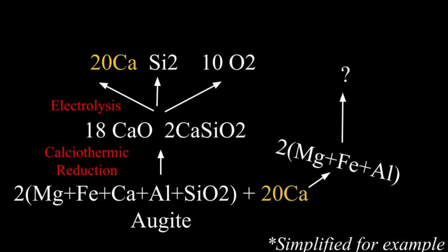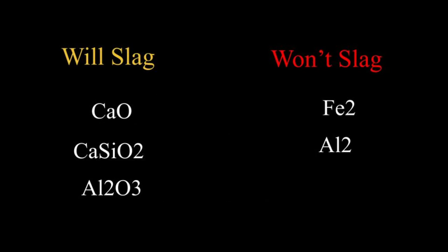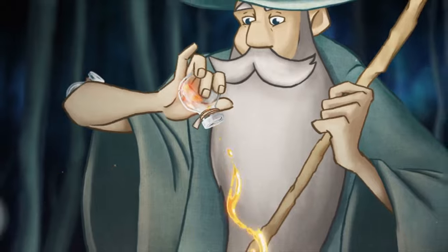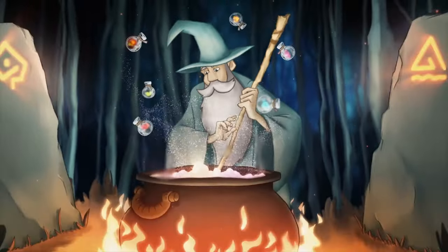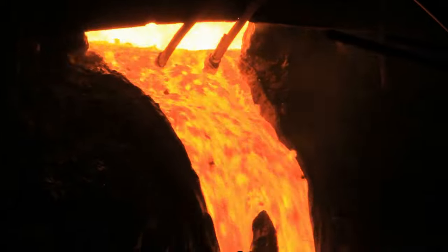But we're still left with an alloy, mostly iron and aluminum, which, upon having their oxygen removed, will sink to the bottom and dissolve into each other. So we've won a battle, but not the war. Sometimes pure aluminum metal is added with calcium metal as a co-reducing agent, forming calcium and aluminum oxides, which both slag at the top and can be mechanically removed. The problem is we are starting with calcium oxide, not pure aluminum. So I wondered if there was a way to add just enough calcium to reduce everything but the aluminum, leaving it as aluminum oxide, so it could be removed.